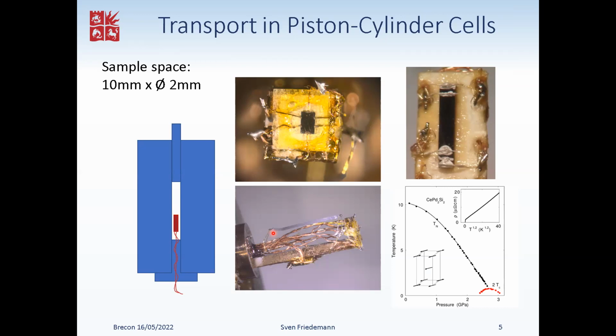Then other pressure gauges: fundamentally there are primary pressure gauges, like calculating the lattice constants of sodium chloride from first principles as a function of pressure. You could use that by doing X-ray diffraction, measuring those lattice constants. You can figure out the pressures in a pressure cell with essentially a primary gauge.